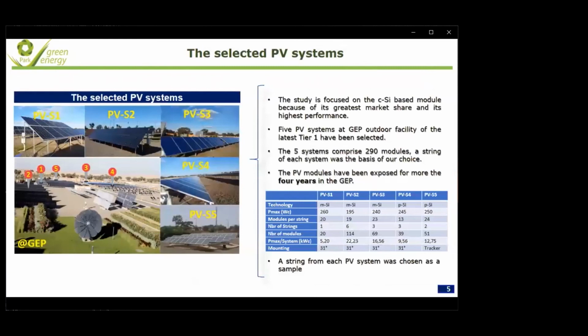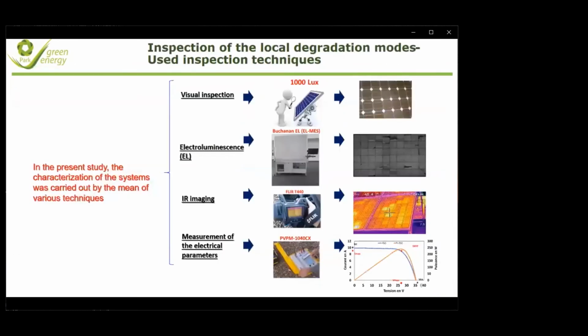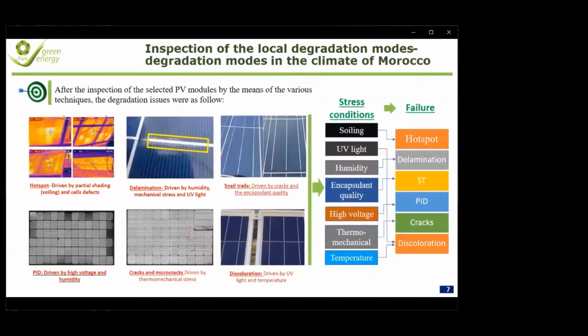In the present study, we focused on the crystalline technology by selecting 5 PV systems from 5 different manufacturers. For each system, we select a PV string as a sample. For the inspection of the module degradation mechanism in the Green Energy Park platform, we resorted to advanced techniques like electroluminescence, infrared imaging, and the measurement of the electrical parameters, in addition to the visual inspection. As a result, after the inspection of the selected PV modules, various degradation modes relating to the climate of Morocco have been observed and detected. These degradations are manifested as hotspots, delamination, snail trails, PID, cracks, microcracks, and discoloration.